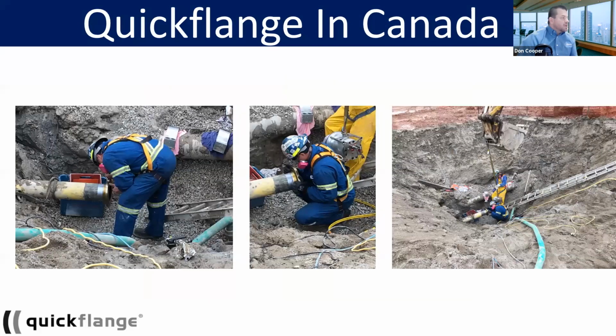Now here is a third example. This is a refinery in Sarnia, Ontario, and this was an underground 6-inch propane line that the client needed to do a tie-in on. They had a lot of concerns with LELs. They had a major welding concern because of the presence of benzene. And we were able to cut and prep the line, fit the flange, and hydro test, and the entire activity, including the confined space into the trench, or I don't know if you'd call that a trench so much as a hole, was performed, the total activity for everything was 6 hours.